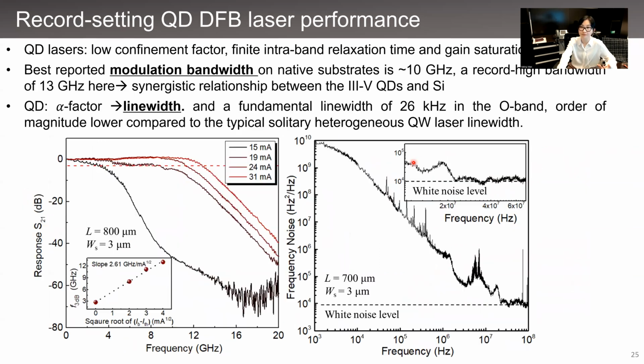And in general, very high modulation bandwidth is very difficult to obtain for quantum dot lasers due to the lower confinement factor and a finite intra-band relaxation time and gain saturation effect. So today, even the best reported modulation bandwidth of the O-band quantum dot laser grown on a native substrate is limited to just around 10 gigahertz.